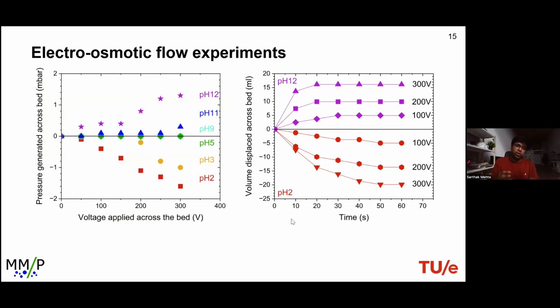An important thing to note here is that pH 2 and 3 experience an opposite direction of flow because they have a positive zeta potential, and pH 11 and 12 lie on the other side of the flow because they have a negative zeta potential.